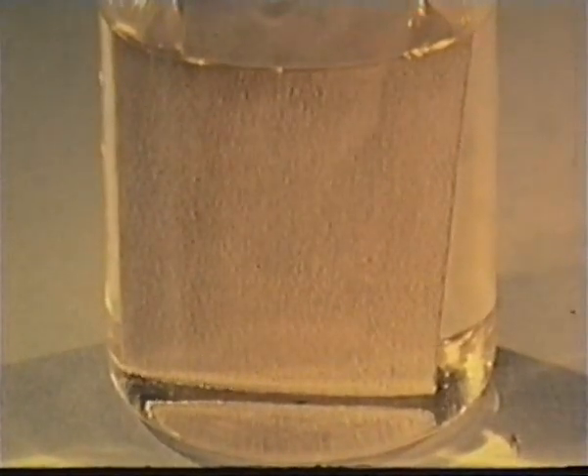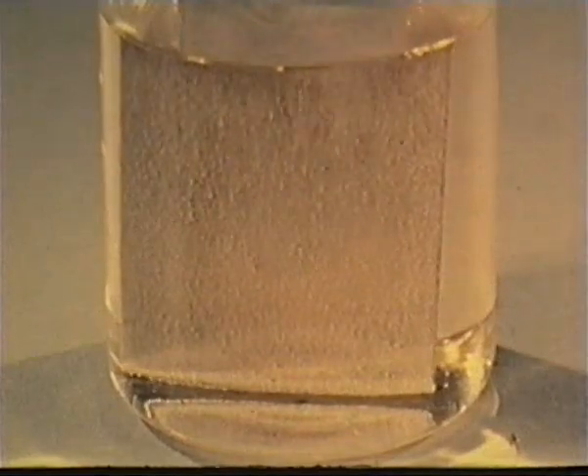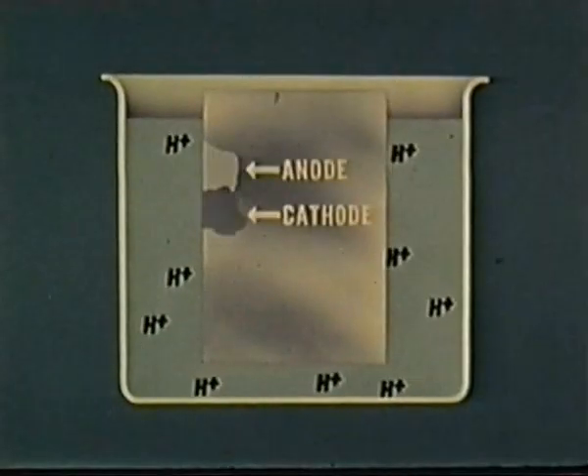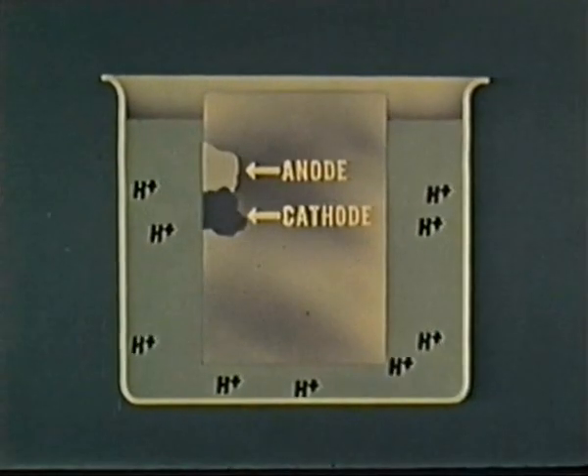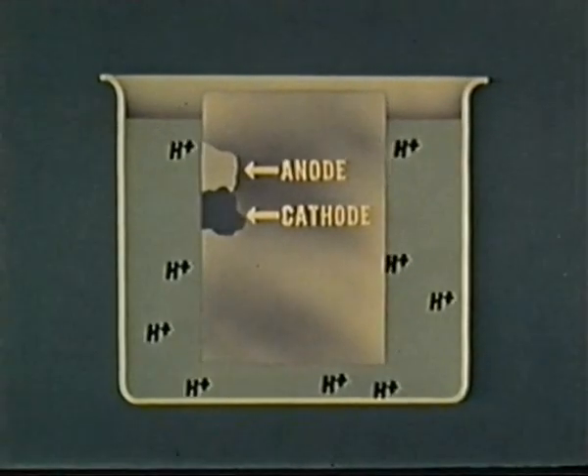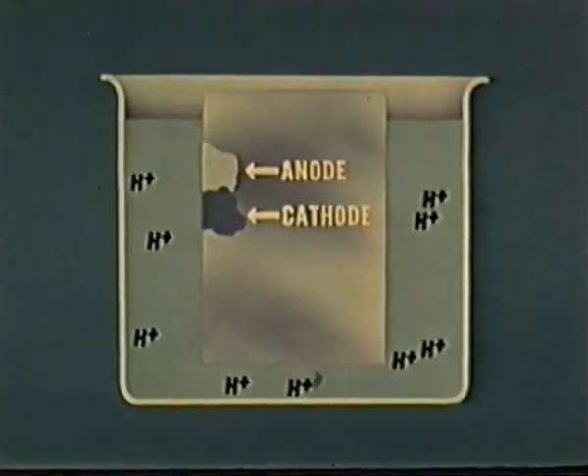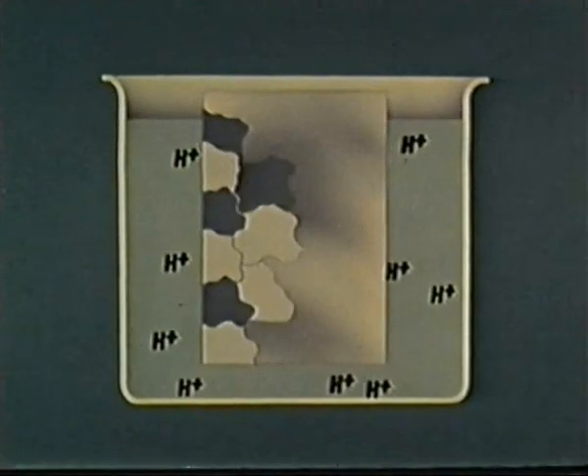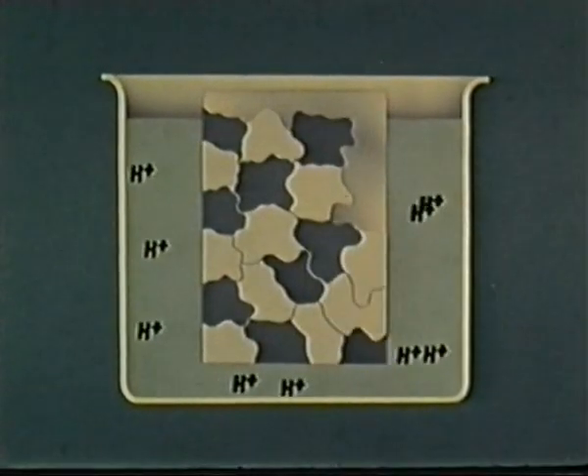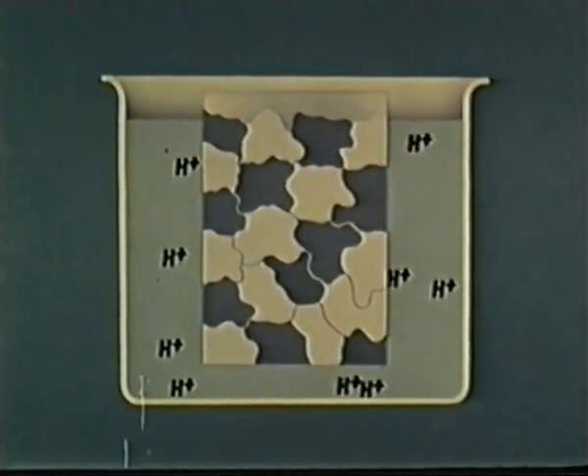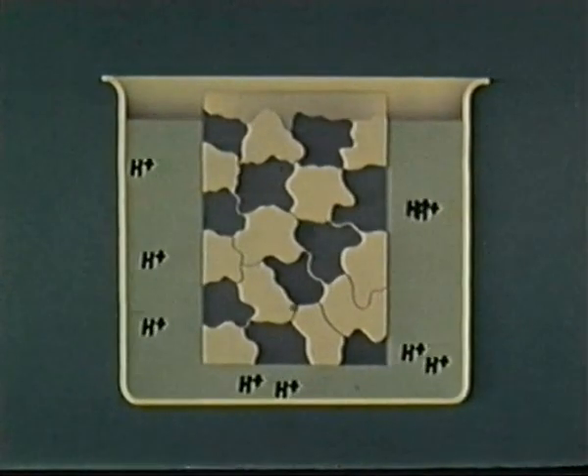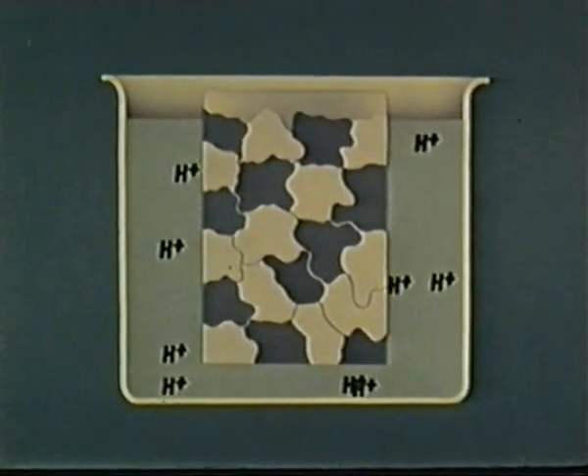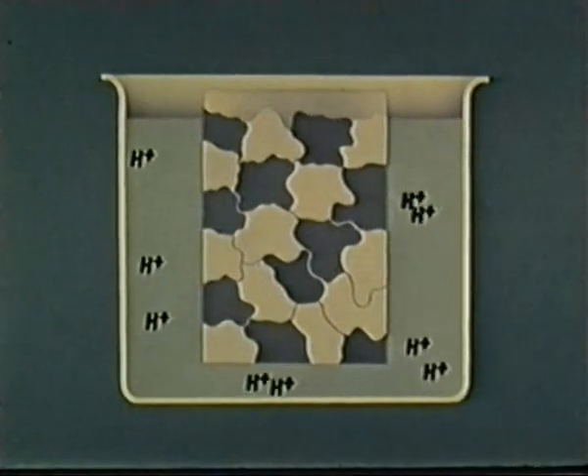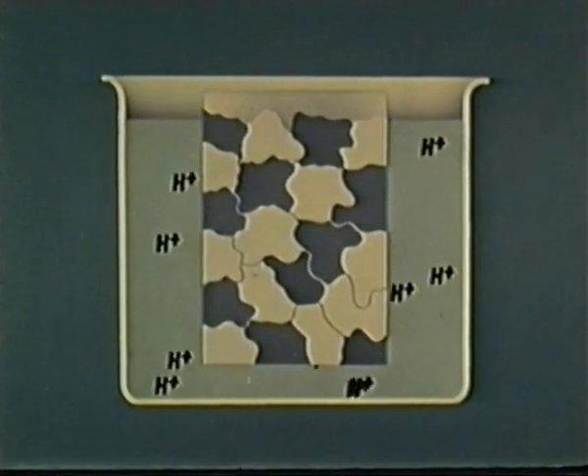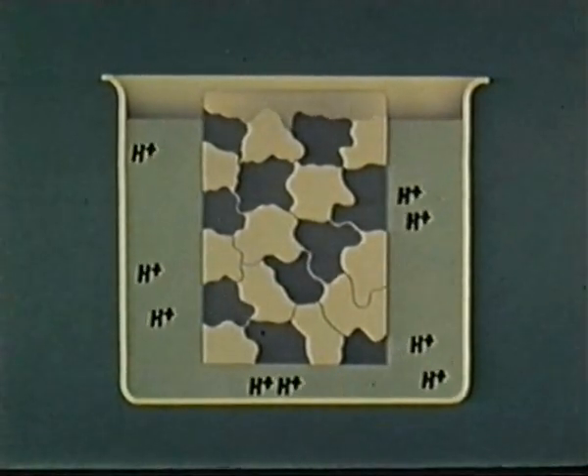If we could see this action through a powerful microscope, we would see many tiny anode and cathode areas on the surface of the metal. These areas are often extremely small and so numerous as to be almost inseparable. There are many causes for this, such as inclusions in the metal, lack of homogeneity, surface imperfections, orientation of grains, localized stresses, and also variations in environment.